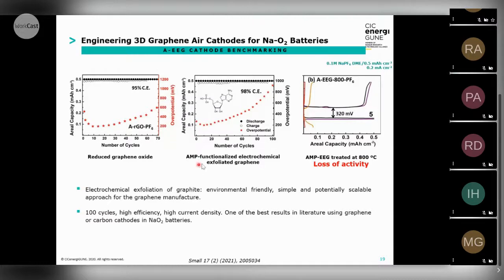If we go to the case of AMP-functionalized electrochemical exfoliated graphene, we can see that we can perform 100 cycles, 30 more than in the case of RGO, but the overpotential in this case was increasing more rapidly to 900 millivolts at 100 cycles. And in the case of the heat-treated sample at 800, there is loss of activity because the AMP is no longer on the surface of the graphene. That is an XPS analysis that you can find in this publication.